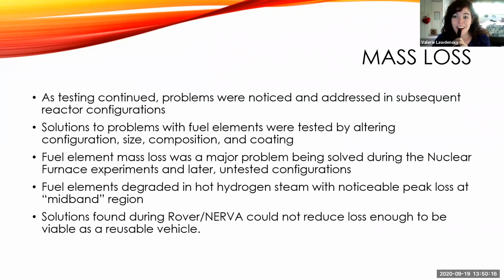And the reason I have investigated coatings and whatnot is because of a noted problem in those early experiments, a substantial mass loss along these channels. Now, a fuel element itself is not this long. It is significantly longer. It's about 1 meter. And there are hundreds of these in any given reactor.